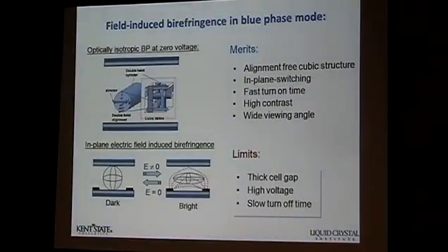And normally they are chiral materials, right? This is the reason that we want to learn about the viscosity of the material. Cholesteric is already very high, and you're trying to twist the helix smaller and smaller to form this double helix, and then what does that mean in the induced blue phase material? Okay, we're talking about the induced blue phase material, not the intrinsic blue phase material. So you need to add a lot of chiral additives, or use some kind of chiral additive that has a high helical twisting power. So that's the alternative.